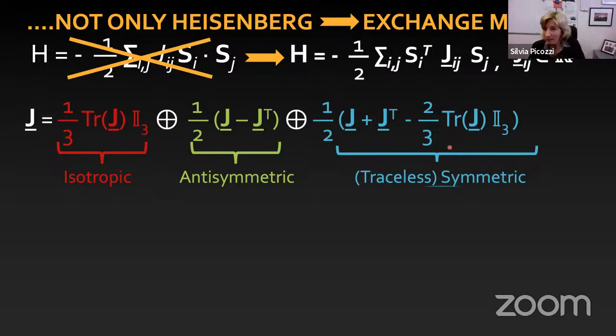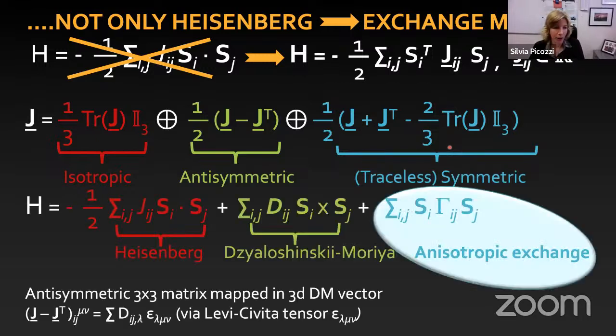So if I now look at their physical meaning, this first term is usually the Heisenberg term. This second, antisymmetric one is what people call the Dzyaloshinskii-Moriya interaction, a cross product of the 2 spins. And then we are left with this third term, which is something people usually don't calculate. It's usually very, very small, but it's there. It's called anisotropic exchange.